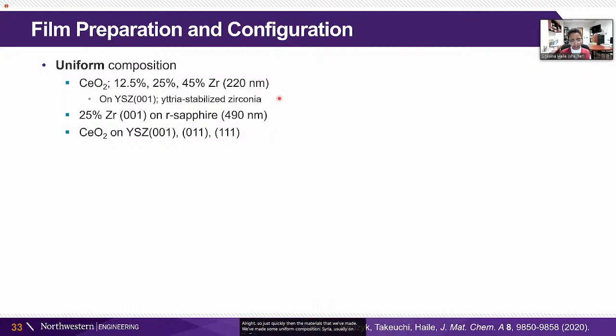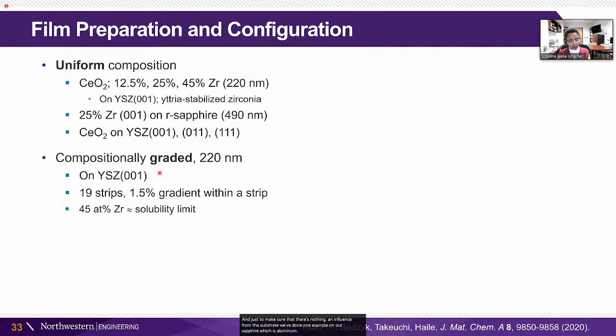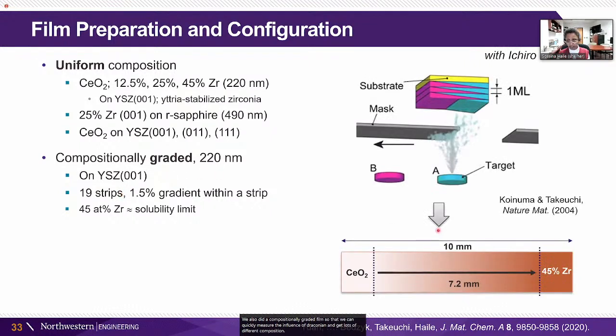All right, so just quickly then, the materials that we've made: some uniform composition ceria, usually on yttria-stabilized zirconia substrates, and we've done 3 different orientations. And just to make sure that there's no influence from the substrate, we've done one example on sapphire, which is alumina. We also did a compositionally graded film so that we could quickly measure the influence of zirconium. And get lots of different compositions essentially in one fell swoop.